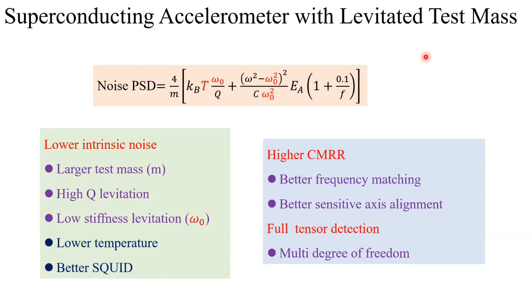What should we do? Of course, the first one is we want to increase the test mass. For the first one, it is only 8.7 grams, which is too small. So we want to increase this. And then we want to have a higher quality factor to lower the thermal noise, and lower the levitation stiffness, so the test mass can move more freely and be more sensitive to the signals that drive it.